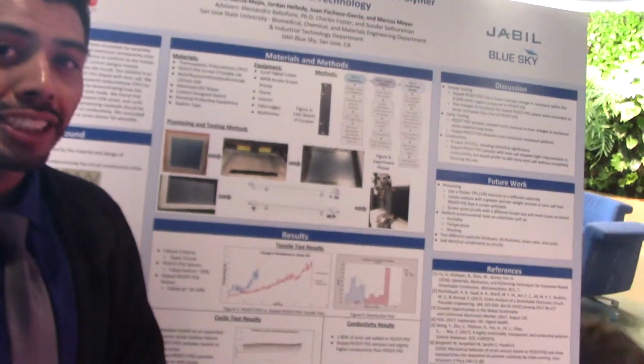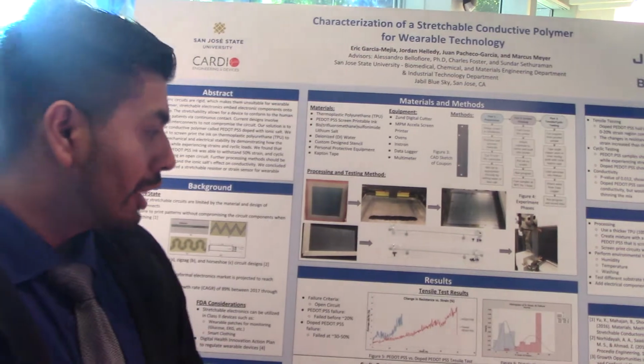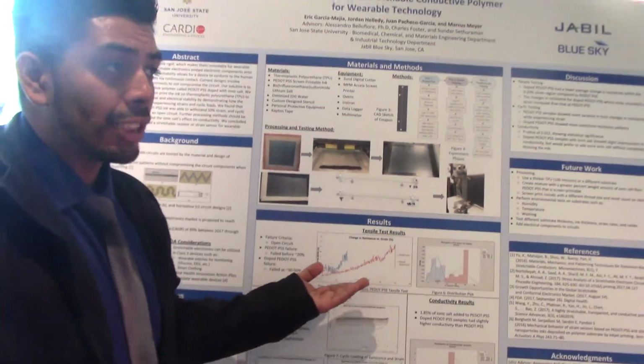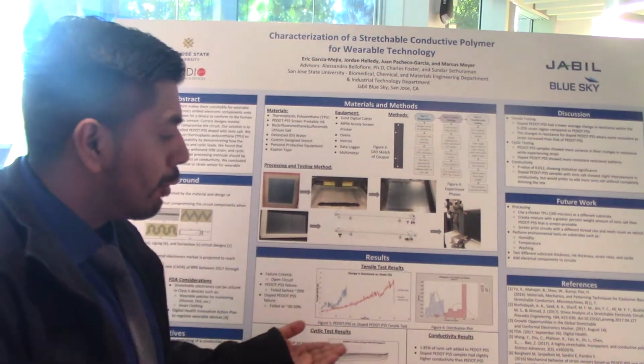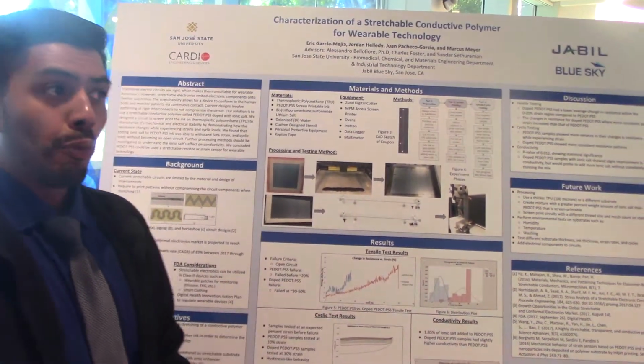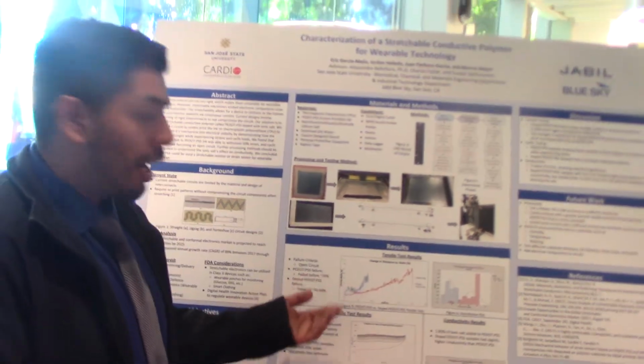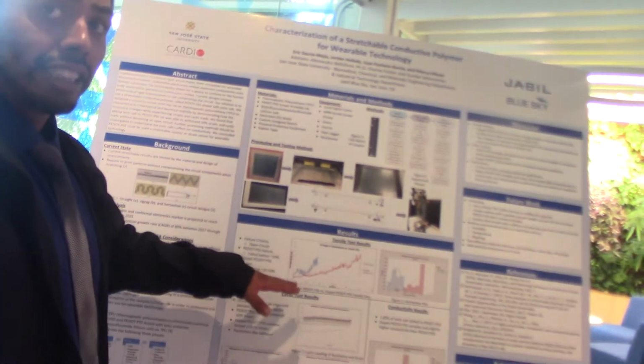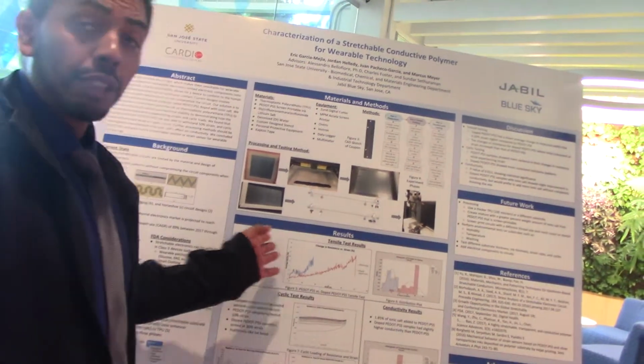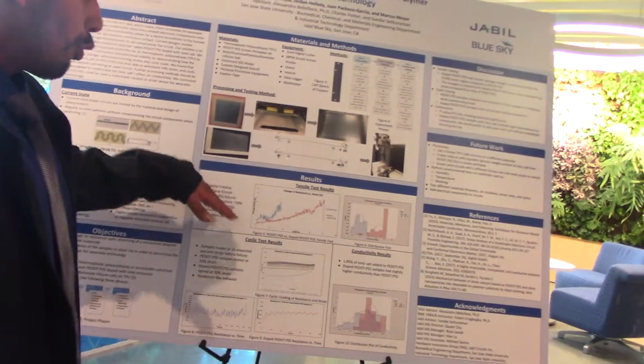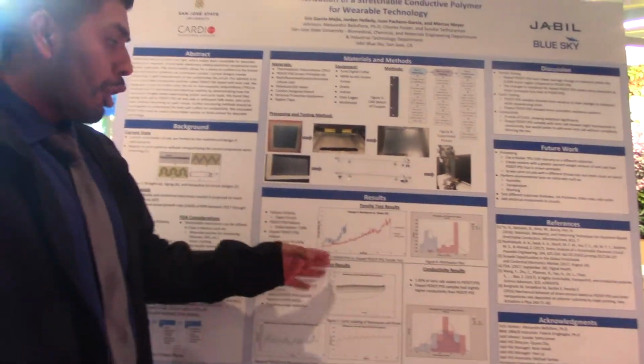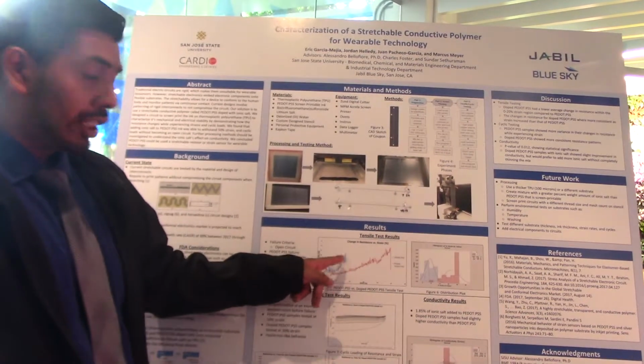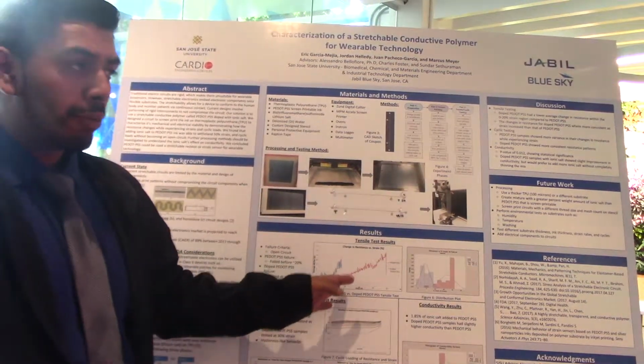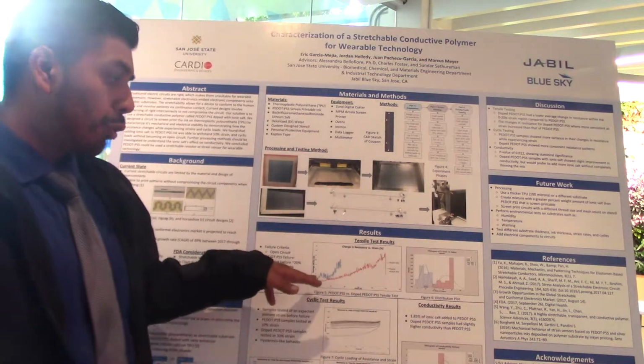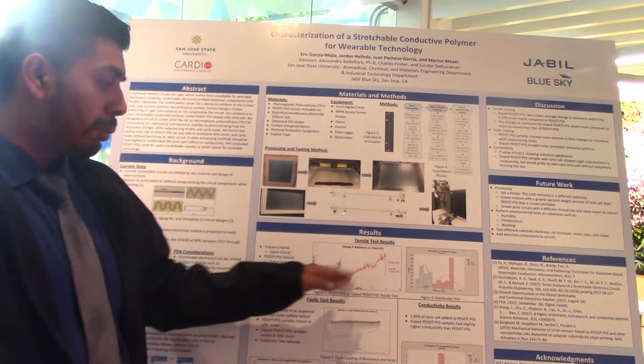So for our testing, as probably mentioned before, we did tensile testing and cyclic testing. For our tensile test, we saw that PEDOT:PSS with our lithium salt additive was able to withstand up to 50% strain without failing, while our PEDOT:PSS without it in the blue was only able to withstand about 18. This is an average change in resistance over strain, and we also see that there's a big jump in the resistance and the change in resistance right at the 18% mark, whereas the doped PEDOT:PSS is able to withstand up to the 50% and keep a low resistance.